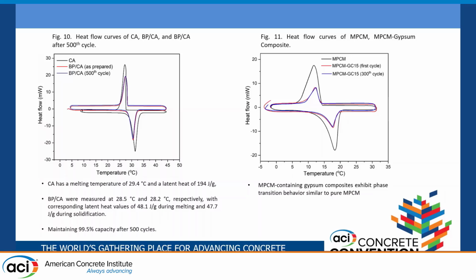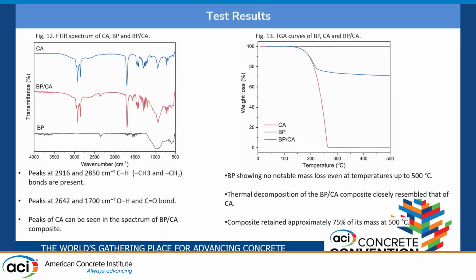Again, we did the same for the microencapsulated PCM and the gypsum composite. While we're doing shape-stabilized PCM, we need to understand the interaction between the porous material and the PCM: is it a physical interaction or is there a chemical bond here? As you can see, I'm not going to go into detail about the bonds that we have observed, but both capric acid and the composite have quite similar FTIR peaks. So this shows us that we don't have any new peaks while incorporating PCM into the basalt powder. This shows us that this interaction is purely physical. We don't see any chemical interaction here.